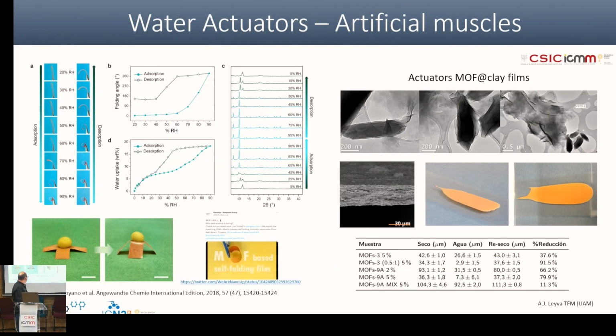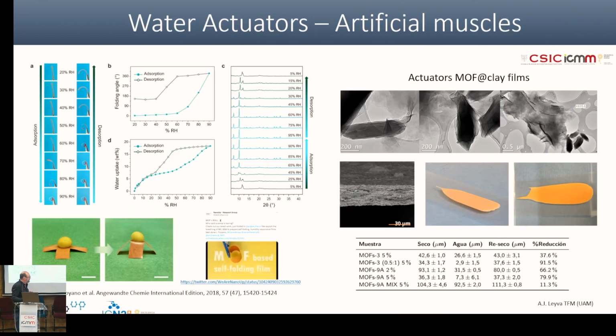What we can do with that one is, Javier Troyano from my previous group in NanoApp said, flexibility is nice, but you know, I'm preparing that kind of films with polymers, mixed matrix membranes for separation, with a flexible MOF, but I cannot characterize it. It's folding all the time. It's turning all the time. I prepare this, I go out of the oven, I get this, and then I need to put it again stiff to collect the XRD, but I cannot. And okay, oh sorry. So he said, I don't mind anymore. Let's make a paper with this.